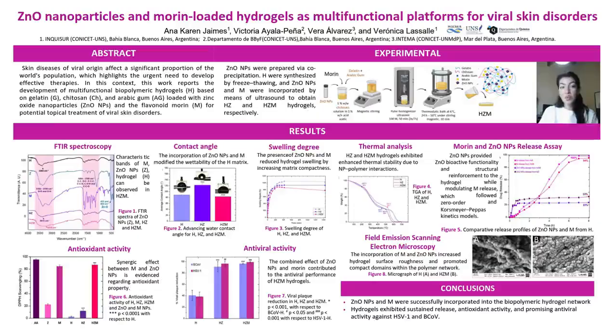Overall, these results demonstrate that zinc oxide nanoparticles and Morin were successfully incorporated into the biopolymeric hydrogel network, providing sustained release, antioxidant activity, promising antiviral activity against herpes simplex virus type 1 and bovine coronavirus, and structural stability, highlighting the potential of these hydrogels as a multifunctional platform for topical antiviral applications.